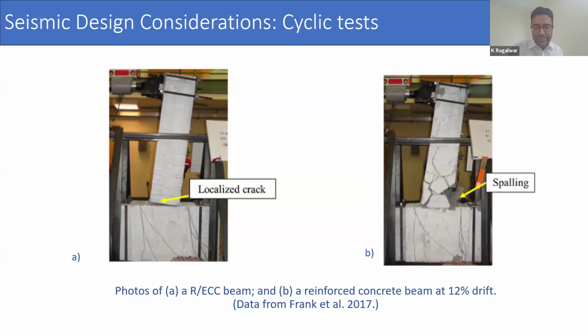Now compare that to reinforced HPFRCC beams with the same reinforcement ratio. Instead of just a few cracks, we see a network of many cracks, which was also visible in the previous slide. These are kept narrow because fibers bridge across them, which not only prevents the spalling but also provides lateral restraint to the reinforcing bar, so that way the bars are not buckling.